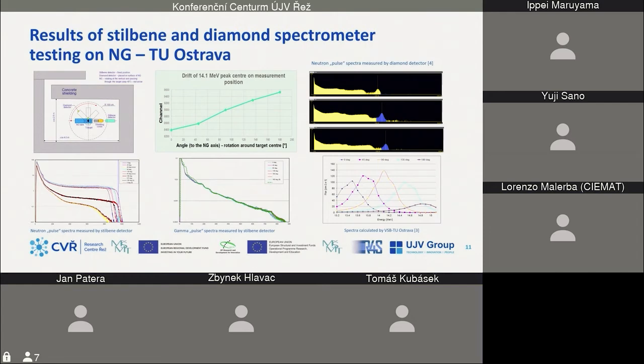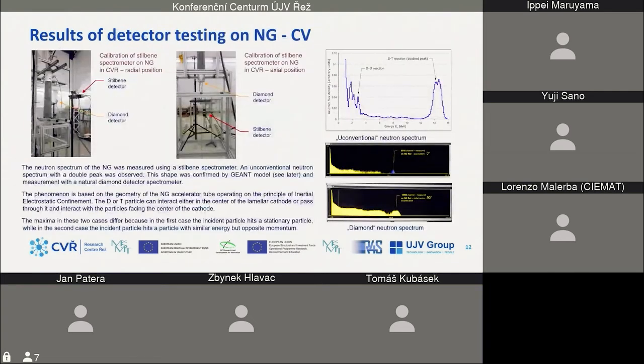So this is the second step. We have tested our spectrometry equipment on different unknown sources and verified it with a different spectrometer. The last measurement we performed was at our neutron generator. What was interesting, and unexpected, was that the peak of the 14 MeV was doubled.